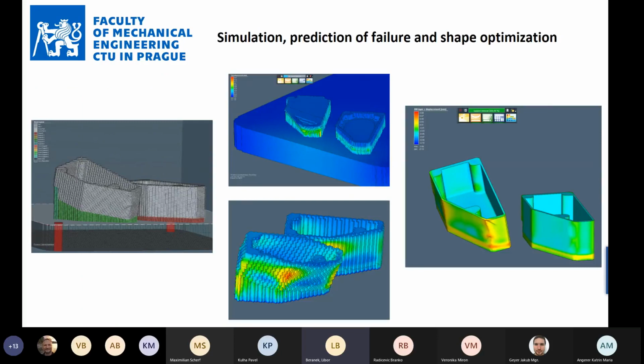Regarding the simulation or prediction of failure, this comes into play when you have asymmetrical parts or parts with very thin walls, because the most common problem is that the thermal history of the part will deform the part so that it will rise above the powder bed. This is the moment where you can easily have a collision with the recoater system. So you have to be very careful that the part deformation doesn't exceed a certain limit, and that these deformations don't come out of the powder bed, because then they will be higher than the level where you are moving with the recoater, and you can easily hit it, causing a mechanical collision of the production tool.